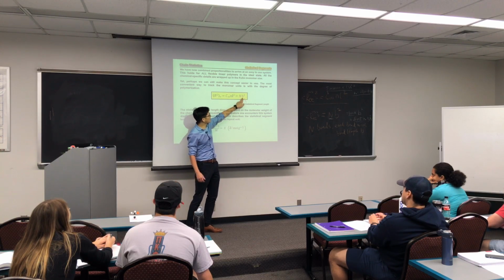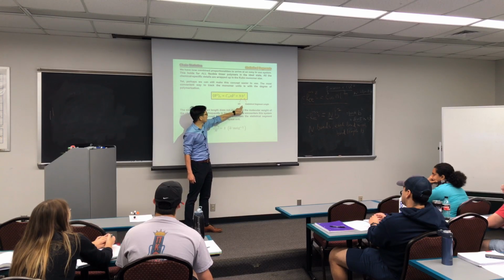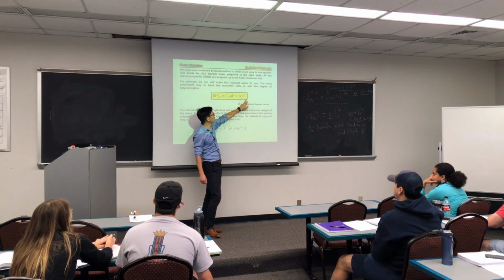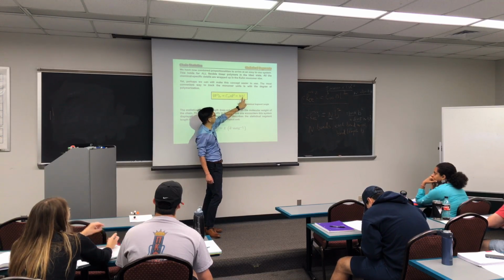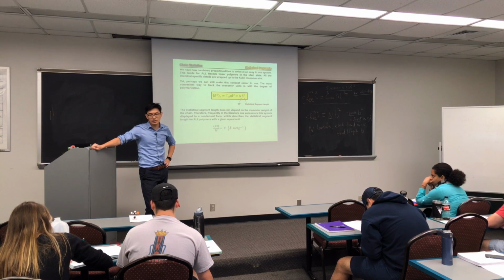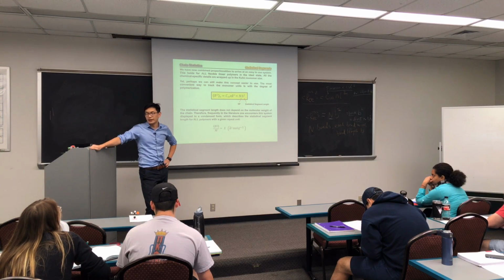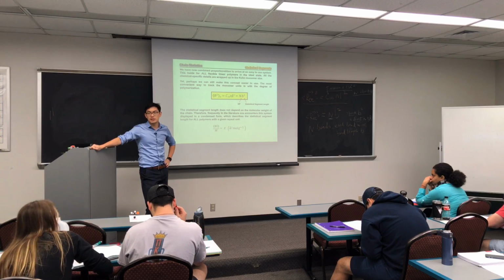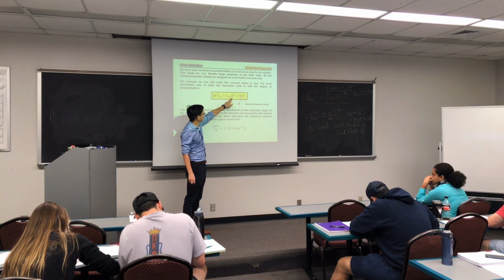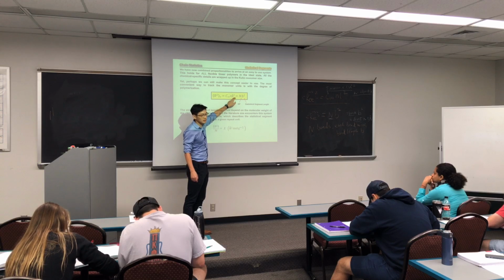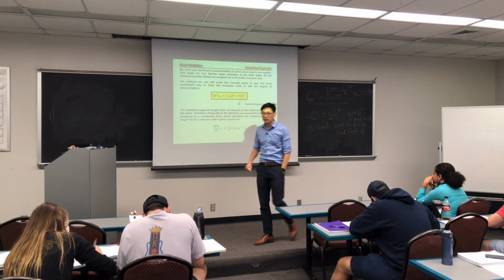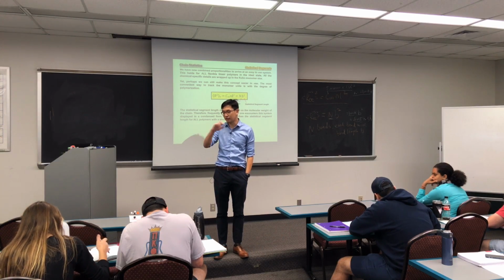However, equivalently, if you have the degree of polymerization, you can get a statistical segment length and use a freely jointed chain model to describe it. That would give you N b squared. If you look at the textbook, there is a table that tells you what the statistical b value is, and you will see the b value is much larger than the original bond length. So if your bond length is 1.5 angstrom for polyethylene, your statistical segment length will be about 5 angstrom, 3 times bigger. And if you search the textbook, it has an extensive table.